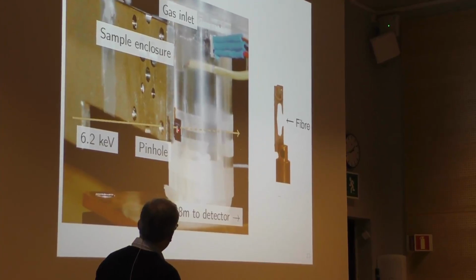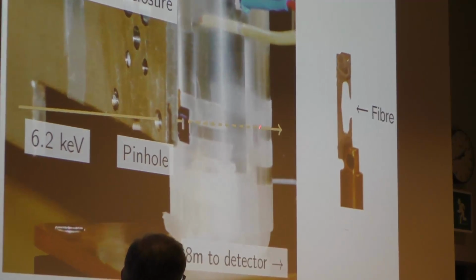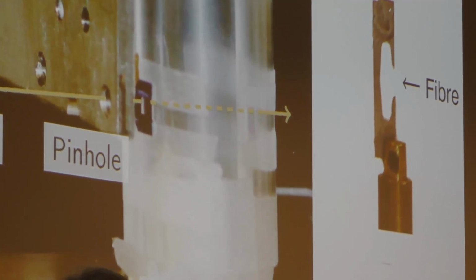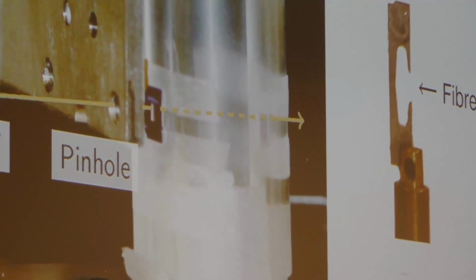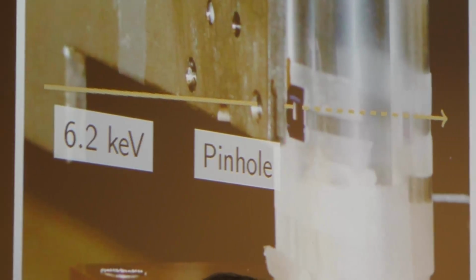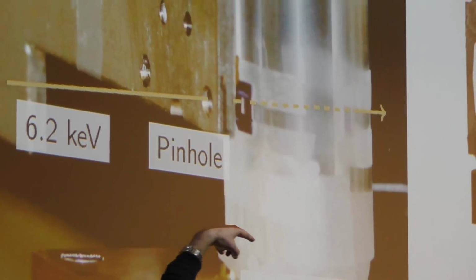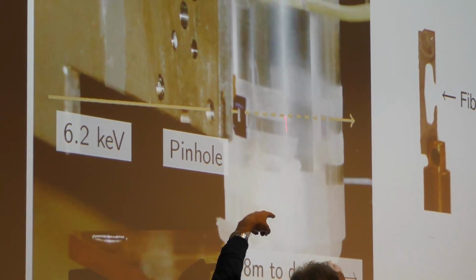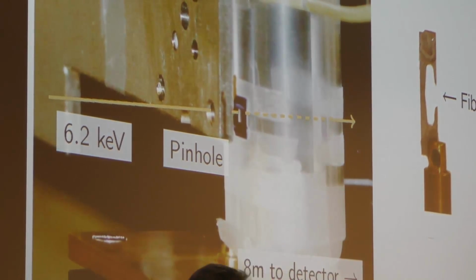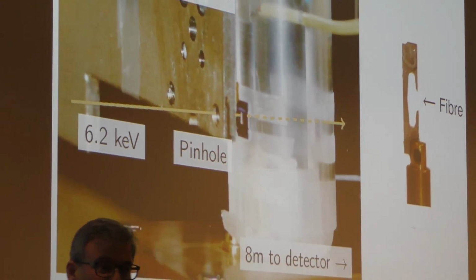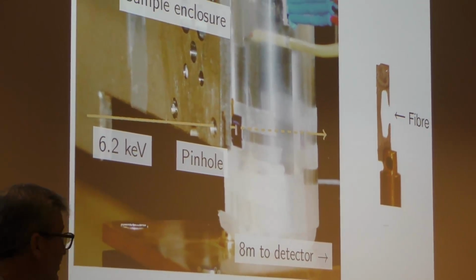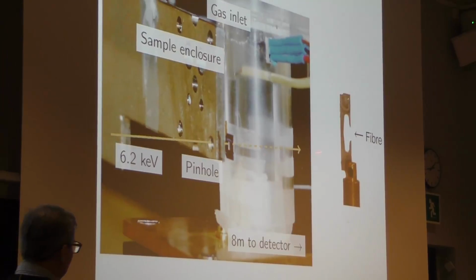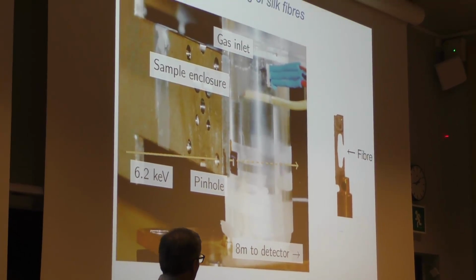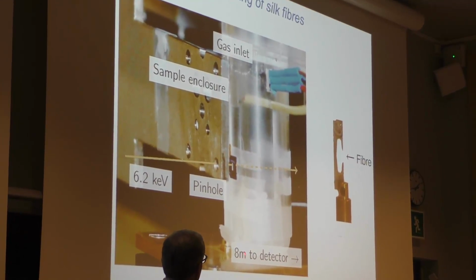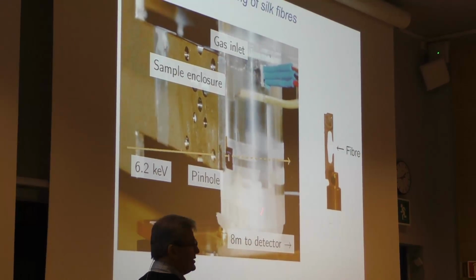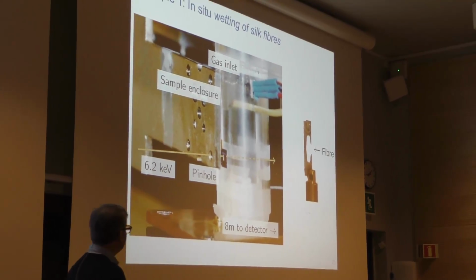And these, here we have one window and here another window on the back side. The coherent X-ray beam is coming in here. And as I told you, the silk fiber is inside of this enclosure, which is used in such a way that we can measure the X-ray signal coming out on the other side. And of course we can vary the humidity then inside of this enclosure.